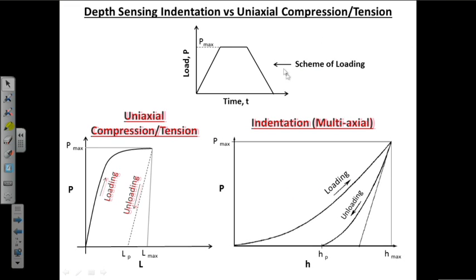This is the scheme of loading which we apply for depth sensing indentation, and the same scheme is essentially applied for uniaxial compression or tension also. We apply a certain load for a certain duration of time, and after a certain amount of time the load reaches P max, and we hold that load for a certain amount of time, which is called the dwelling time, and then we unload the test specimen and reduce the load to 0. If we apply such a scheme during uniaxial compression or tension, the load displacement graph is something like this. Initially the load varies linearly with the applied displacement, and when a certain load is reached, the behavior changes from linear to nonlinear, and we say the material is deforming plastically.